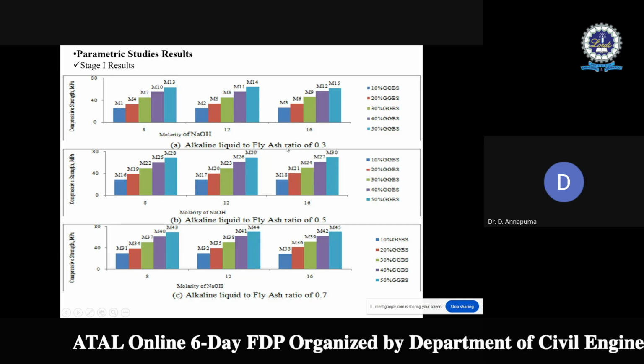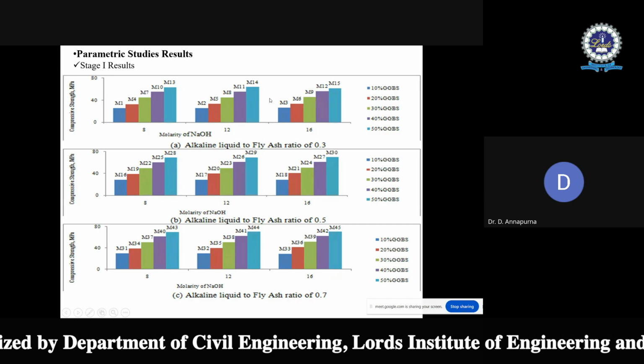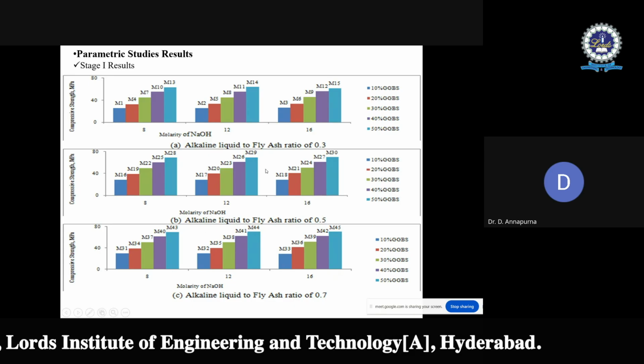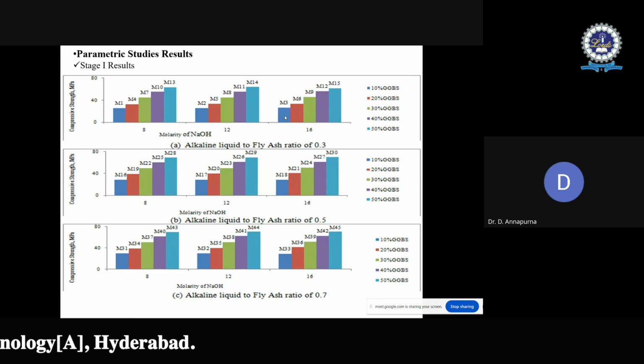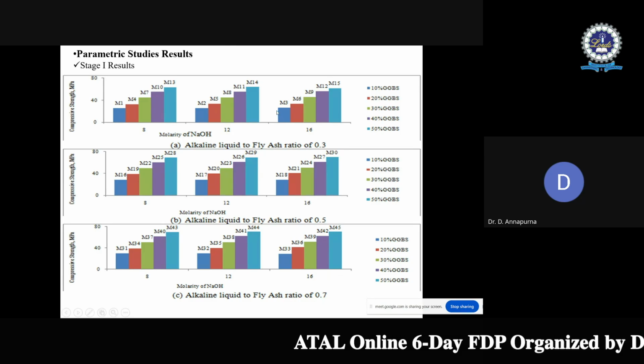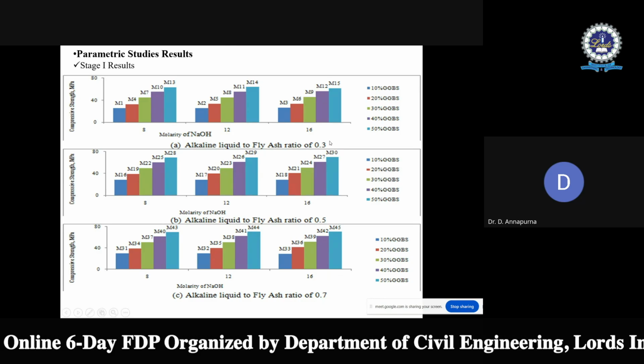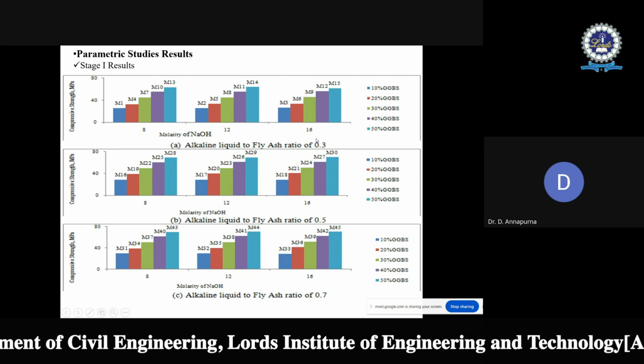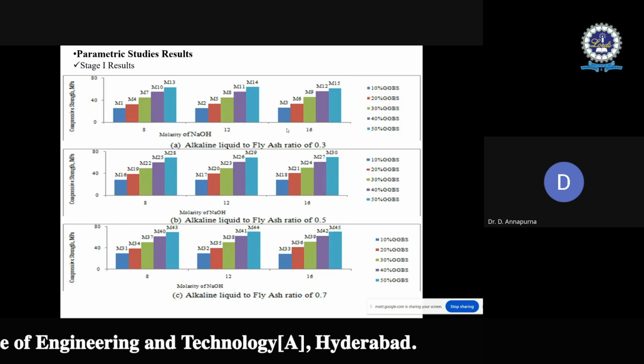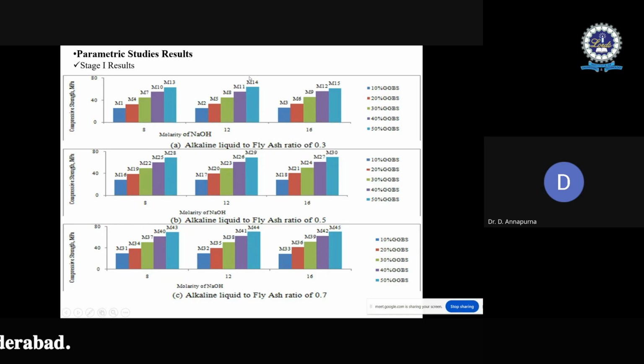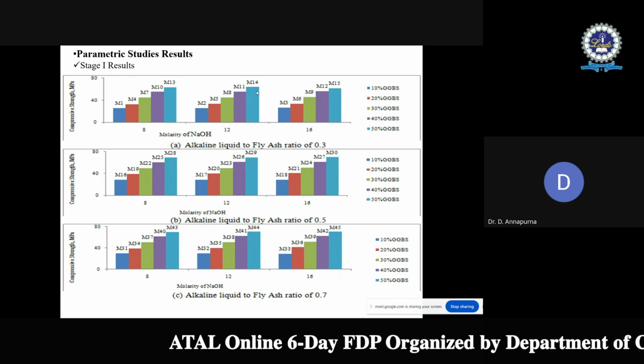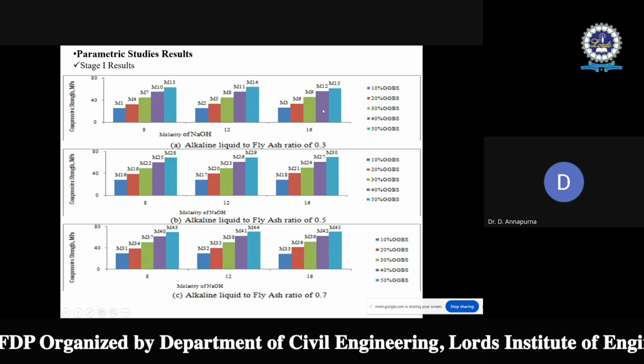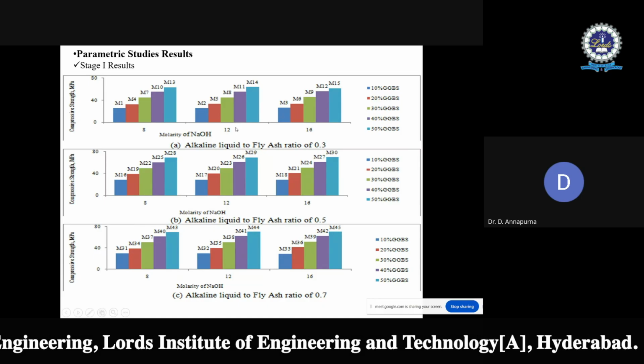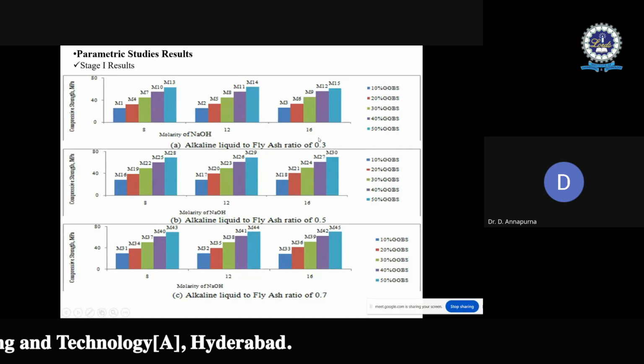The next variation is the alkaline liquid to fly ash ratio. If you look at 0.3, 0.5, 0.7, almost similar results are observed. But when we check how the mix is prepared, the mix with an alkaline liquid to fly ash ratio of 0.3 was very stiff, because the alkaline liquid is very less with the 0.3 ratio. Because it is very less, this mix requires a huge amount of superplasticizer, added up to 10%, which is undesirable, especially for the 16 molarity mix. It consumes more superplasticizer, which is not desirable. That is the reason this 0.3 mix was not used for further stages.